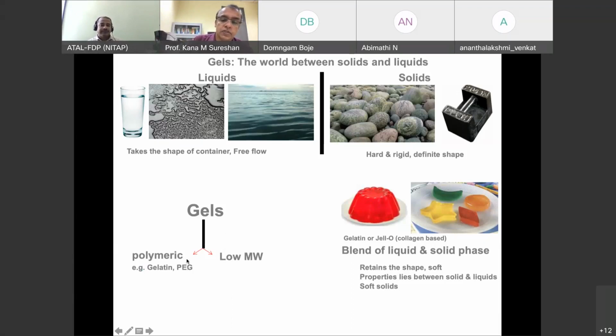And also there are other polyethylene glycols that can form gel, higher polyethylene glycols. Then comes low molecular weight organogelators or hydrogelators. These are very small molecules, usually less than 500 molecular weight, and they can also self-assemble to form a fibrillar network. They are not polymers themselves, they are monomers actually, but they can form a non-covalent polymer in some solvents. That non-covalent polymer makes a mesh, and in the mesh the solvent gets trapped. That's what a low molecular weight organogelator is.